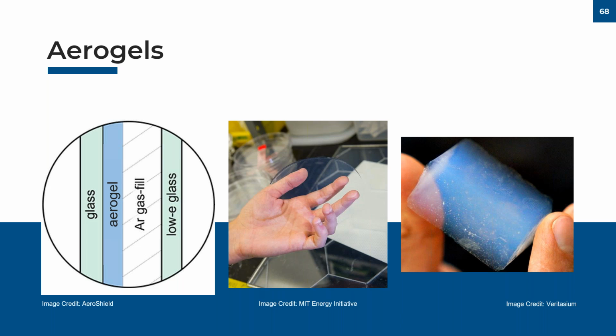Now, one downside historically has been that aerogels have always had this semi-translucent appearance to it, sometimes with a bluish hue, but researchers have found ways to make it significantly more transparent, and now are marrying that aerogel to a sheet of glass. And this is really intended to fit within the same IGU pocket as a conventional dual pane glass, while keeping the overall weight low, and it can be glazed with argon or krypton gas fills, and low E coatings in addition to that.